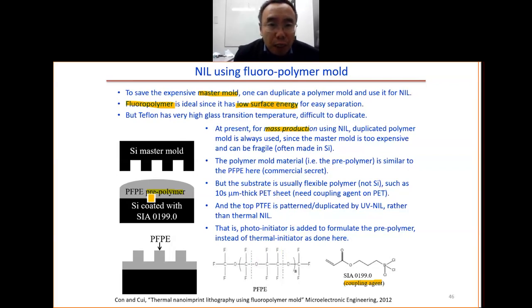But the substrate in this work is silicon. For the mass production, we don't want silicon. So what is used is a PET sheet, a 10 micrometer PET sheet, rather than the fragile silicon. Another difference is that this layer, in this case, is cured by high temperature. But for the production of the polymer mold from the master mold, it is cured by UV imprint lithography, not by thermal lithography.